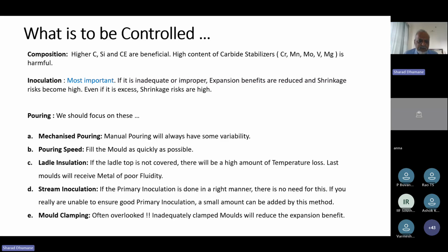Stream inoculation. My own experience is that if primary inoculation is done in the right manner, you don't need stream inoculation. But okay, you can add it to add some comfort factor to ensure that your process remains robust. So a small amount, I think you can add. Whenever you decide to do stream inoculation, don't do excess, because we see that excess inoculation contributes to risk; shrinkage risk becomes higher when inoculation is higher.